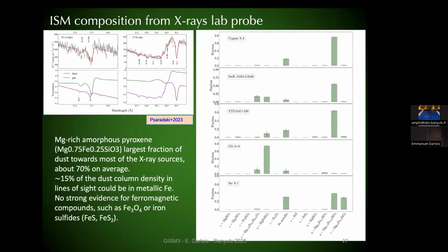More recent observations along different lines of sight, looking at other edges, the iron and oxygen internal electrons, led to different analysis. You have here the different lines of sight observed, and here the different components used in the decomposition, showing that mostly in that case you are dealing with magnesium-rich amorphous pyroxene for most of the sources. Some of the dust in the column density could be in metallic form also. And another important aspect, there is no strong evidence for iron oxides such as hematite or iron sulfide that you find currently in meteorites.